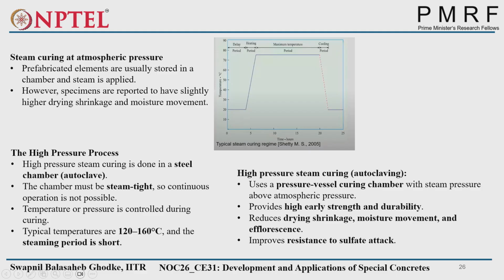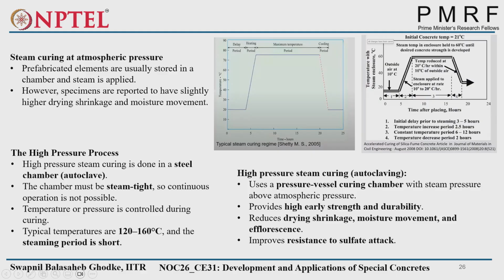In this schematic, you can see how steam curing is done. Initially there is a delay period, and then at a certain rate the heating goes from, suppose, 0 to 50 degrees, at some degrees per hour. Then it stays constant at 50 or 60 degrees Celsius for a certain amount of time. Then the cooling period is also not sudden; it is gradual, and then it comes to normal temperature. So this is the steam curing process.